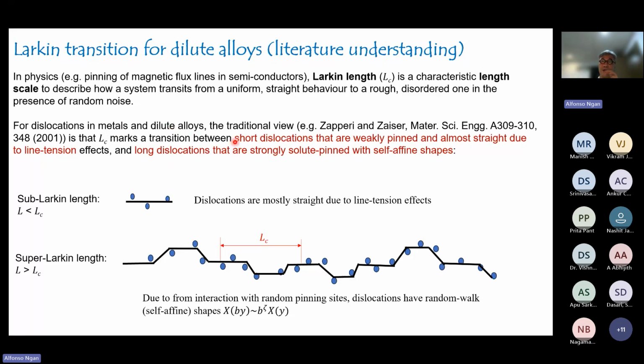So basically, the literature understanding for dilute alloys or pure metals with some impurities would be that at the short length scale, if you look at a dislocation at very high resolution, dislocations are mostly straight. And of course, this is due to the line tension that I talked about in the first slide. So even though there may be local obstacles, such as dilute solute atoms, because the dislocation tries to stay short, its shape is mostly straight. But if you zoom out and look at a very low resolution image of the dislocation, I'll give an example later on in the next slide, the dislocation will adopt a random walk or self-affine behavior.